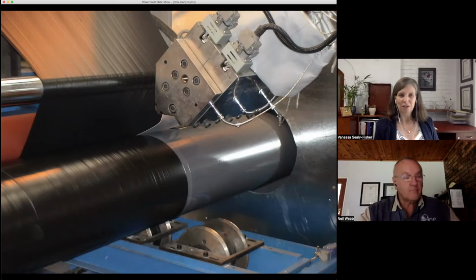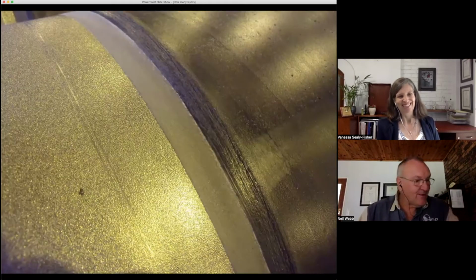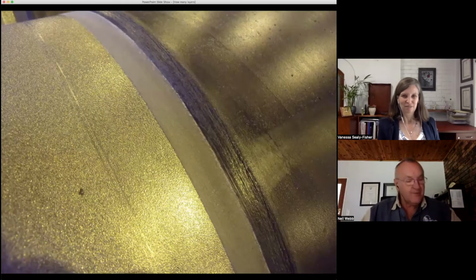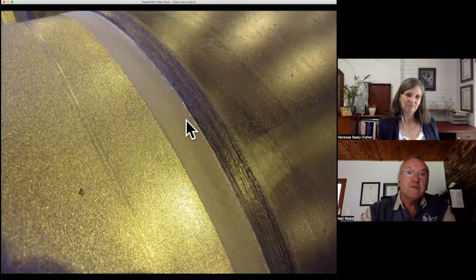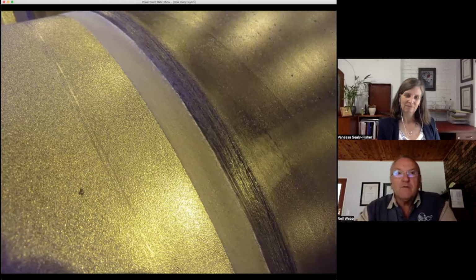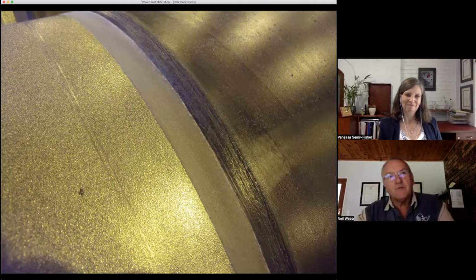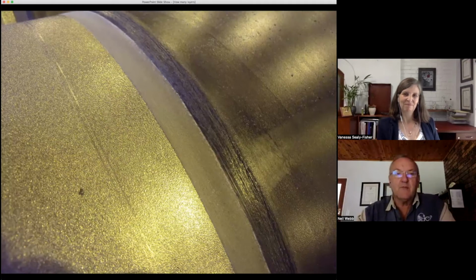So in other words, we now have the perfect coating, or maybe not. Well, I wish. So the 3-layer polyethylene comprises this layer of epoxy in between the steel and the polyethylene on the outside. But it had some issues when it first was produced, because initially the industry thought that it was only necessary to put a smidgen of epoxy onto the steel in order to provide an interface between the steel and the polyethylene.